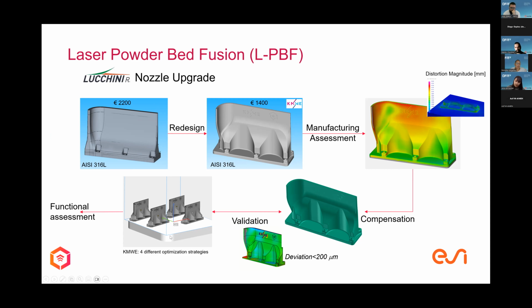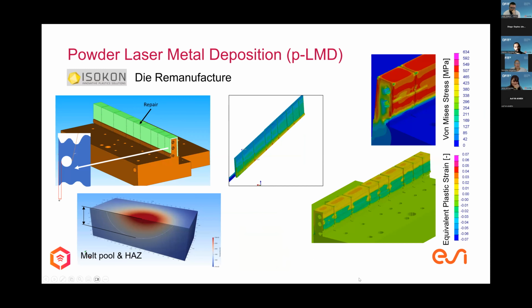And then it was printed by KMWE, 4 different designs and methods to print, and then it goes to functional assessment. An alternative process, powder-based laser metal deposition, was used for the Isokon die refurbishment or repair. We see here that this die surface has a lot of wear and problems which need to be removed via milling. This green volume is the volume which was removed and is to be replaced by a new material.